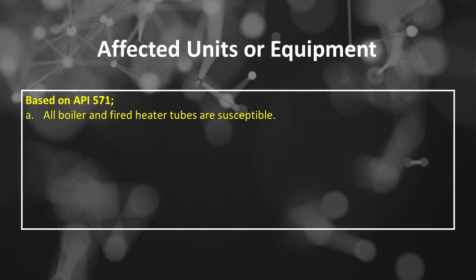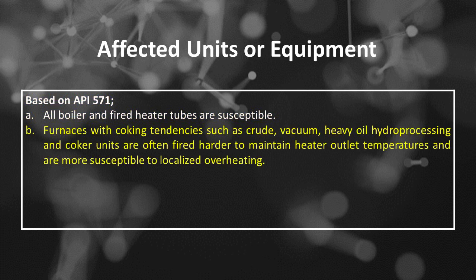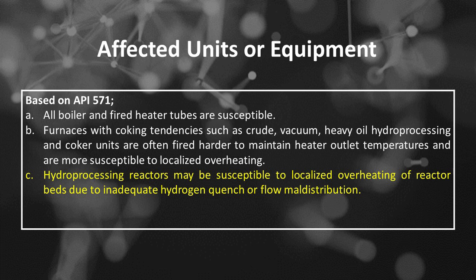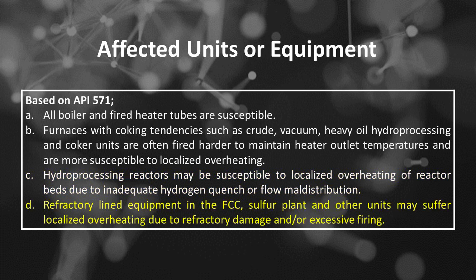Affected units or equipment based on API 571. The first is all boiler and fired heater tubes are susceptible. The second is furnaces with coking tendencies such as crude, vacuum, heavy oil hydroprocessing and coker units are often fired harder to maintain heater outlet temperatures and are more susceptible to localized overheating. The third is hydroprocessing reactors may be susceptible to localized overheating of reactor beds due to inadequate hydrogen quench or flow maldistribution. The fourth is refractory lined equipment in the FCC, sulfur plant and other units may suffer localized overheating due to refractory damage and/or excessive firing.